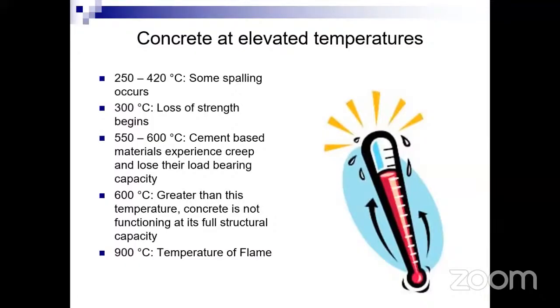Concrete at elevated temperatures: we can see here that when the temperature is around 420 degrees centigrade, from 250 to 420, some spalling will occur in concrete. At 300, loss of strength starts, and then at 550 to 600 degrees centigrade, cement based material experiences creep and loses its load bearing capacity. At 600 degrees centigrade, concrete actually will not be functional, and 900 degrees centigrade is what we are talking about in the flame.